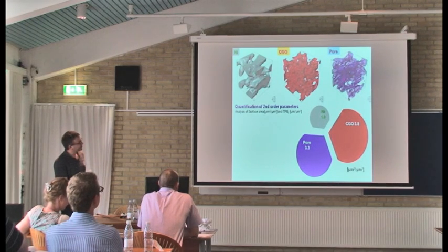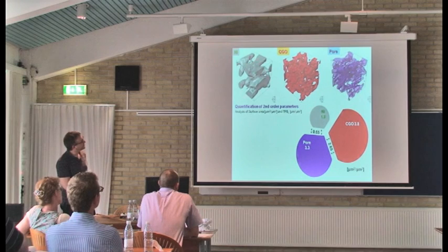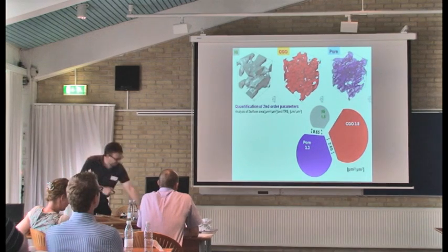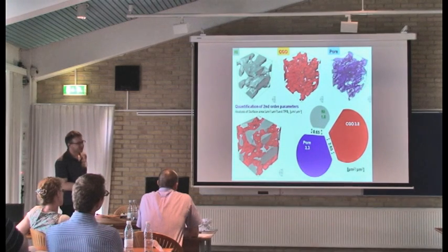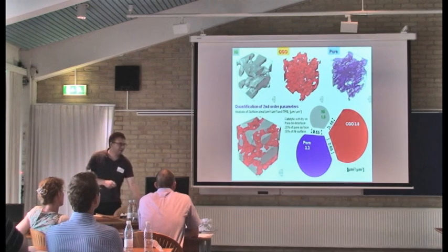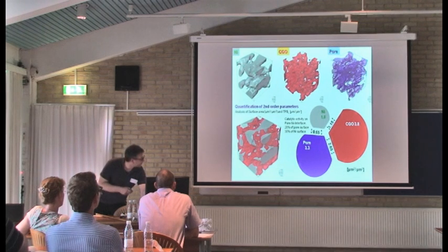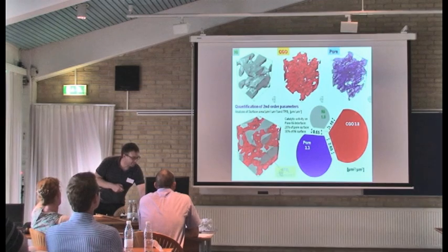Importantly, we can also distinguish, for example, that the pore surface is split into two interfaces. Since the nickel is the coarsest, it has the smallest surface, and then, for example, the pore-nickel interface is much smaller than the pore-CGO interface. This is the catalytic active interface, and that has some impact on the performance. This seems to be a very limiting factor for the formation of the TPB.